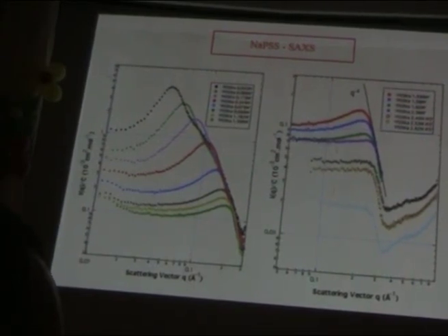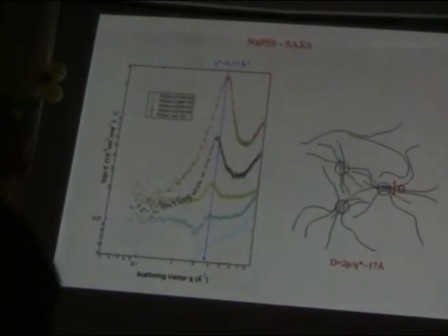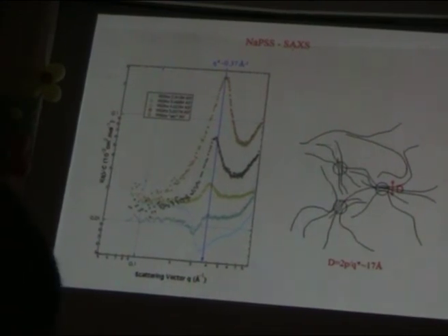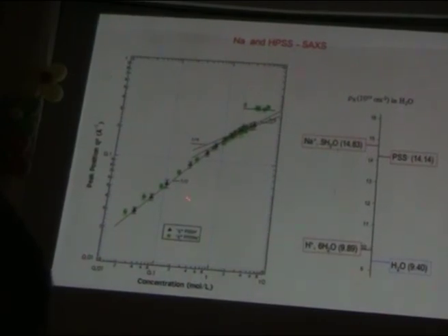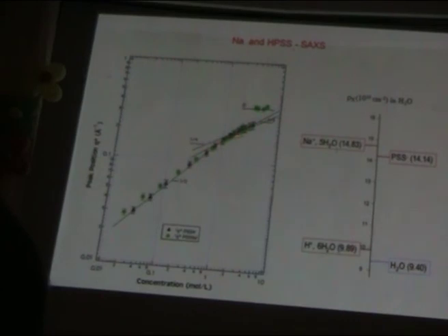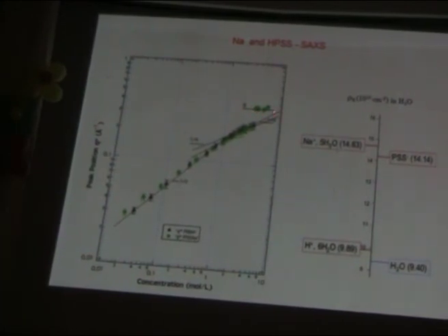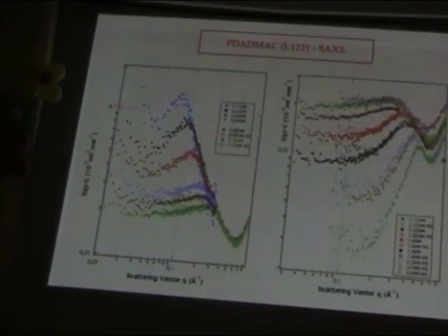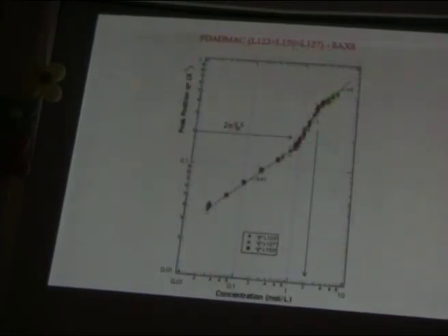At high concentration, you observe what Nishida has observed before. So you have some ionomer regime. I don't want to speak about that. So you see, you observe C to 1/2, C to 1/4, and after something which is a pure ionomer regime, because you have decreased the dielectric constant of the solution, of course, and so you have dipoles here, and you have some association between dipoles. Now if you use PDADMAC, you have the same, but the contrast is lower, of course. And what you are able to observe, you observe the semi-dilute regime, as you will see with the small angle neutron scattering, but you have this Q proportional to C here, and after the nematic regime.